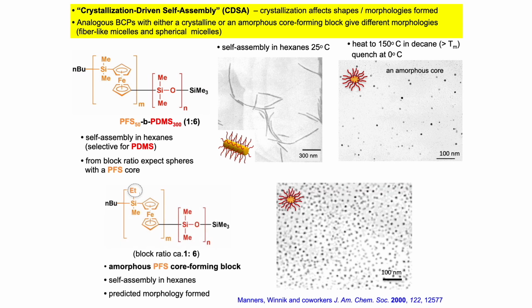And you can demonstrate this further. If you make the same block copolymer, but we now have the PFS block with different substituents so it can't crystallize, even at room temperature, this forms the spherical micelles. Because this block can't crystallize at any temperature. So this is the shape micelle you get, as illustrated here.